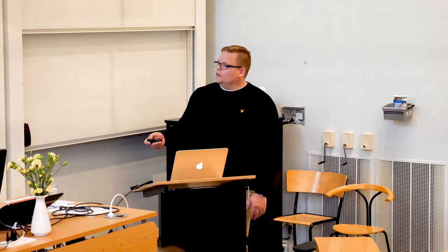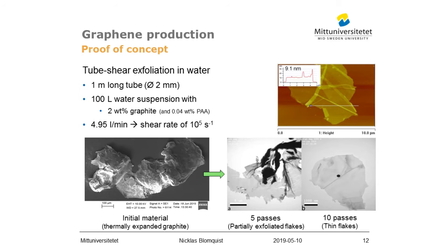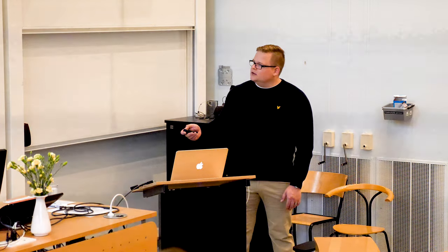The initial material used was this thermally expanded graphite. The scale bar here is 100 micrometers. And when we have passed this initial material through the shear zone five times, we can find a lot of this kind of flakes. Partly exfoliated flakes with thin regions and thick regions. The scale bar here is 5 micrometers. When we exfoliated the material further, 5 more passes, so we had 10 passes through the shear zone in total, it was very easy to find these kind of flakes that are very thin. The scale bar here is 1 micrometer.